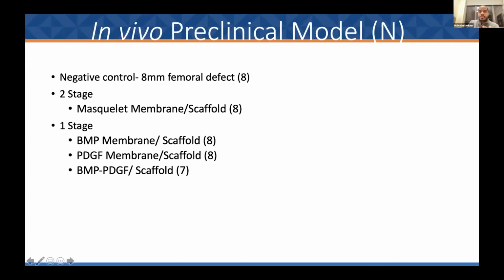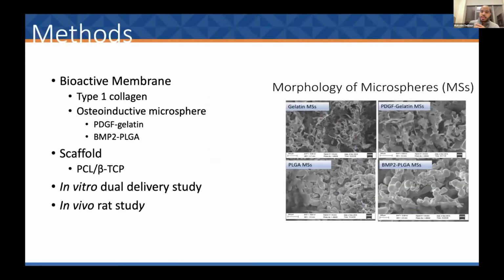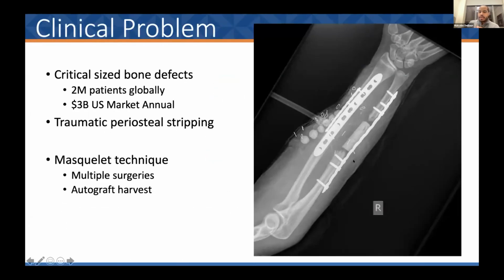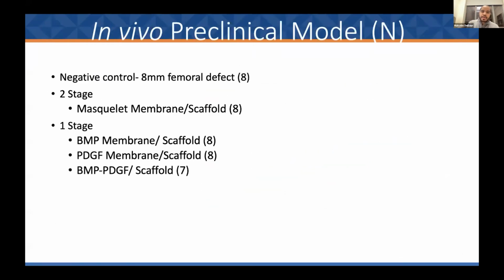So we had a negative control, which is basically a segmental defect in a rat femur that is unable to heal on its own. And then we had the positive control, which is what we do in surgery, the Masquelet technique, which is essentially putting in a cement spacer, which you can see here in the intercalary space. And then that forms a membrane from a foreign body reaction from the patient. And then at 6 to 9 weeks, we come back and size the membrane, take the cement spacer out, and put in bone graft. So we essentially did that in a rat.